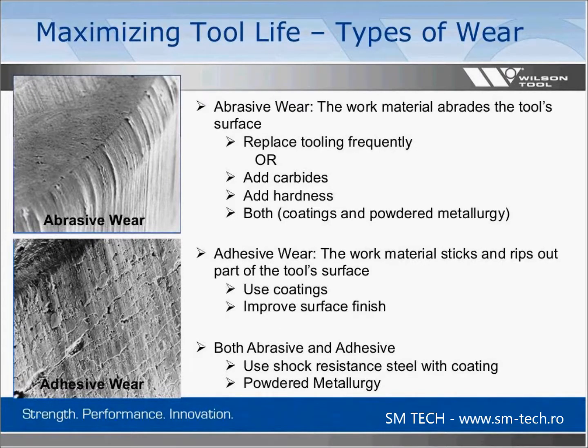If you're experiencing both abrasive and adhesive wear, you can move to a more shock-resistant tool steel and complement it with a surface-enhancing coating. Or you can look at powdered metallurgy, which can actually increase your shock resistance or increase your wear resistance.